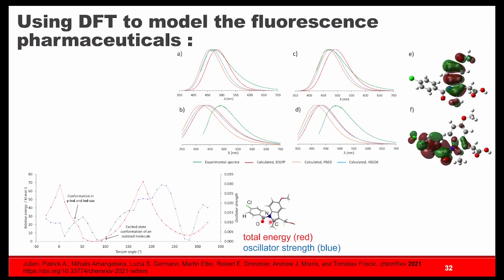Between this carbon, nitrogen, and then carbon and oxygen. And basically that conformation plays a huge role in the overlap of the HOMO and the LUMO. And as you rotate this dihedral angle, you're going to have different configurations, and those are going to change in energy, but we can also look at the change of the oscillator strength. And that oscillator strength strongly correlates with the emission intensity of the molecule.